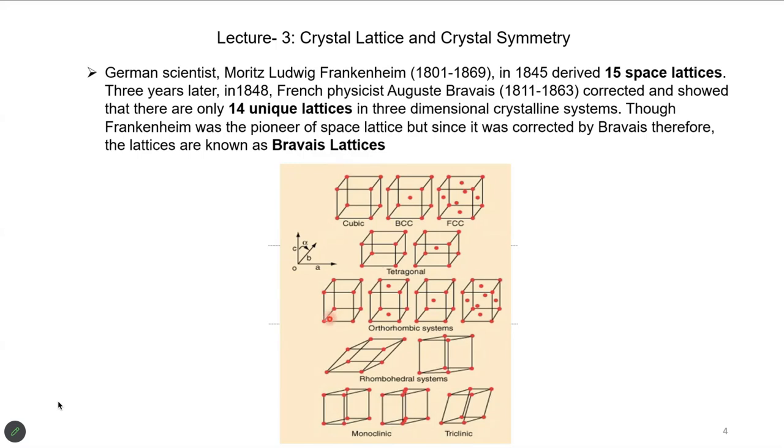Because if we want to determine the three-dimensional structure of a crystal with an experimental technique, we will see that this Bravais lattice plus point group, when we combine, we get 230 space groups. We have millions of crystals, but if we determine their structure, we'll see that crystals must belong to one of the 230 space groups.